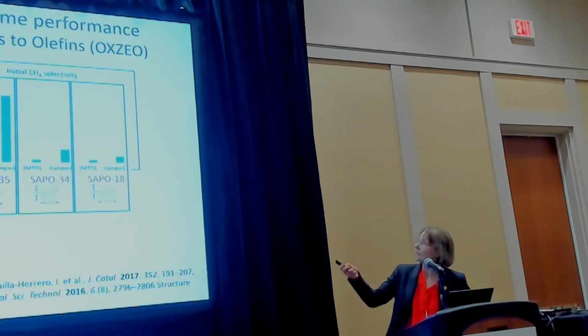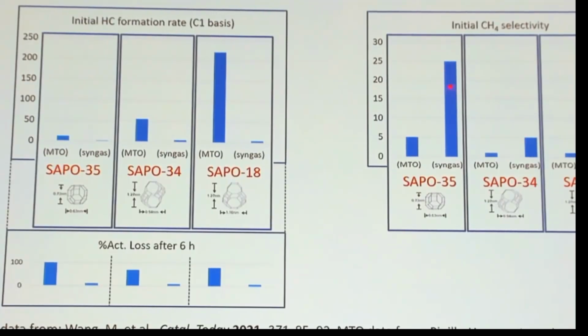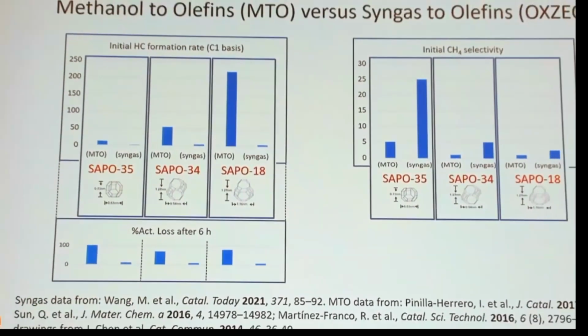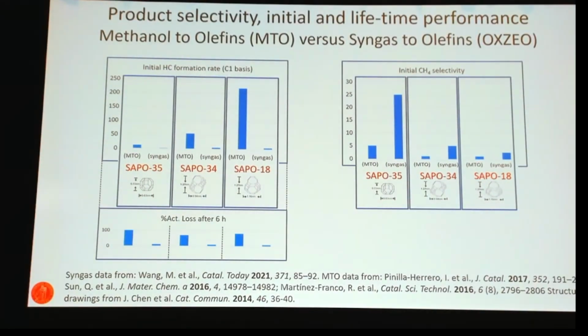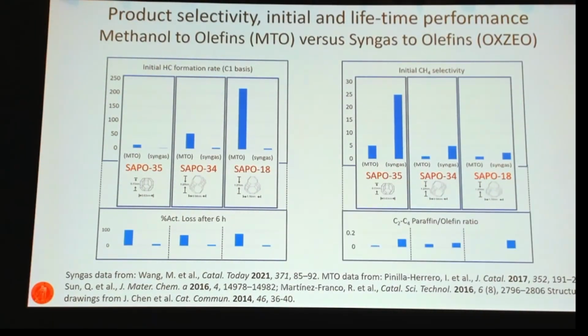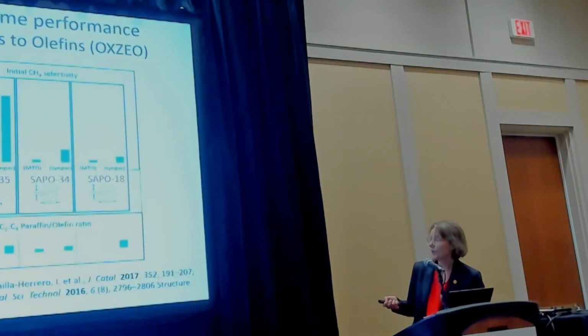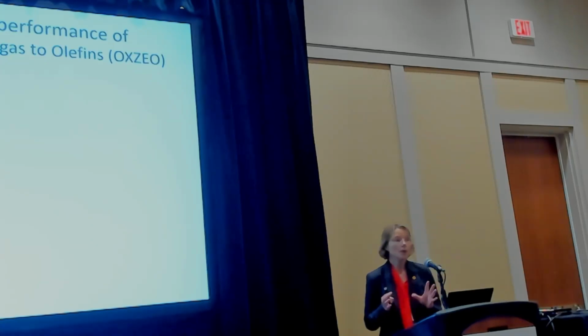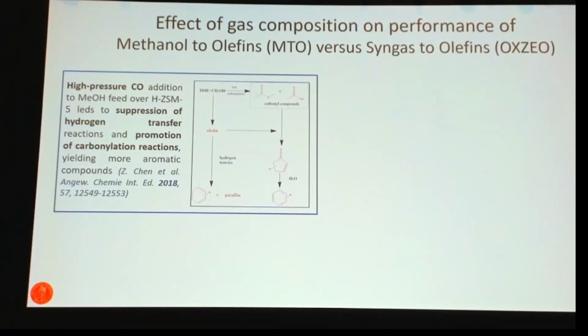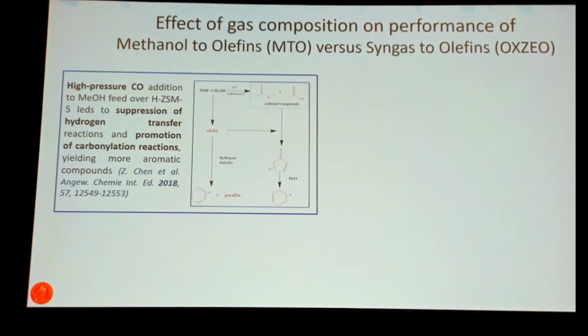And then we see also that the initial methane selectivity is of course higher for the syngas process, and this could be due to the presence of a hydrogenation catalyst, or it could be aldehydes. And we also see that in general the C4 paraffin to olefin ratio follows the same trend. That syngas operation with high hydrogen pressure in the bed leads to more paraffins. Now, the reason could be related to the co-catalyst, the methanol catalyst, but it could also be due to the gas composition, of course.